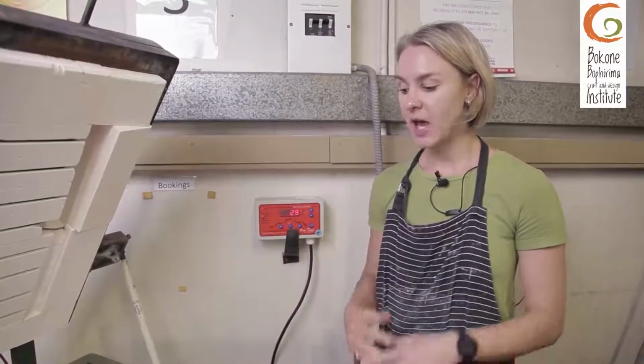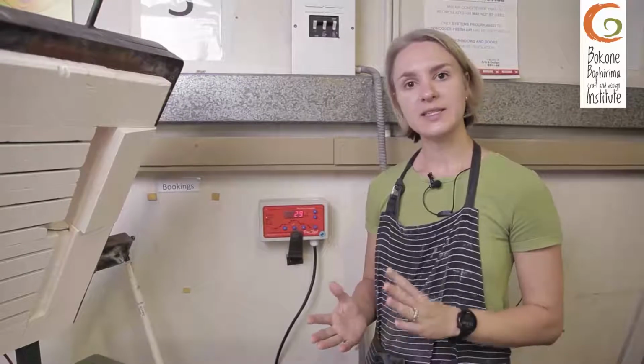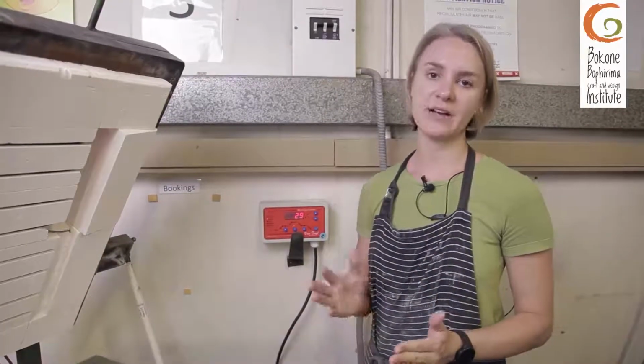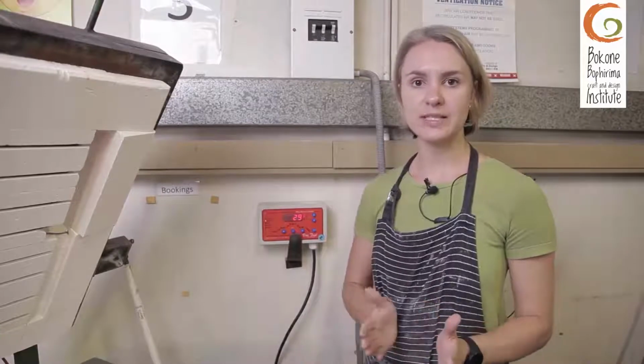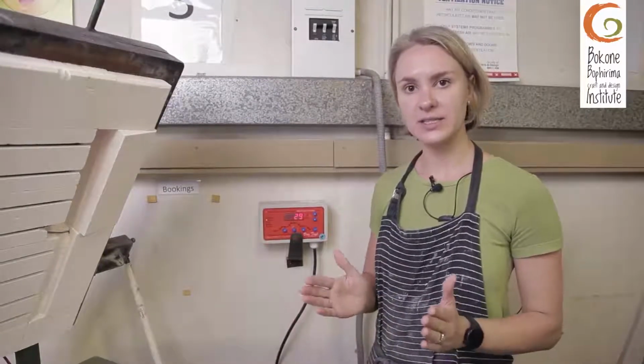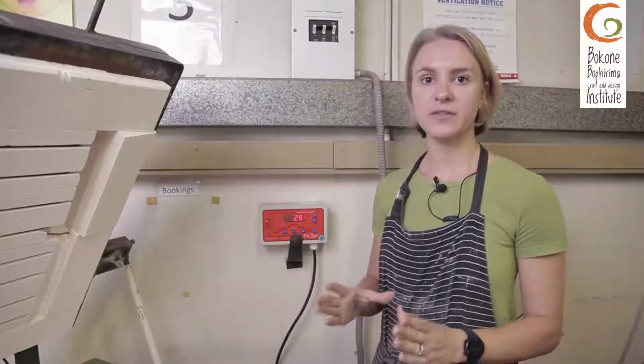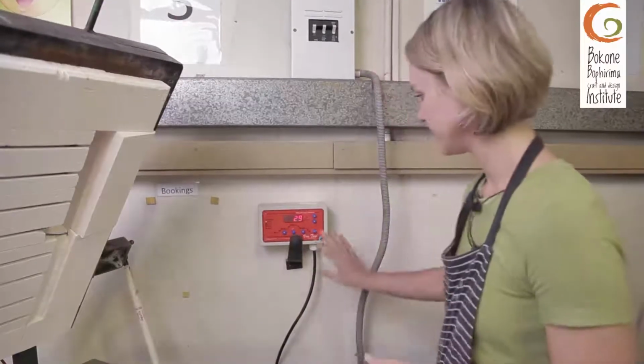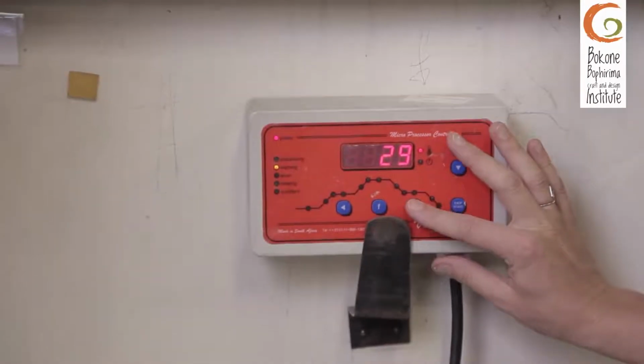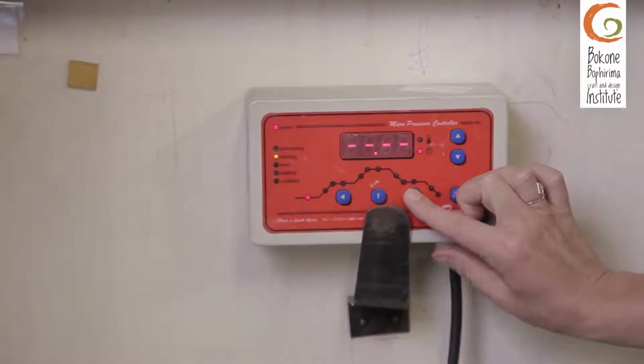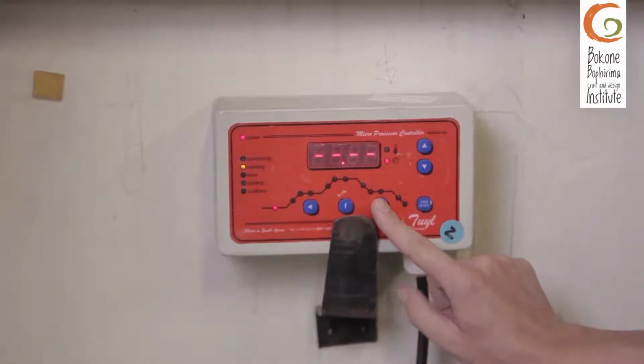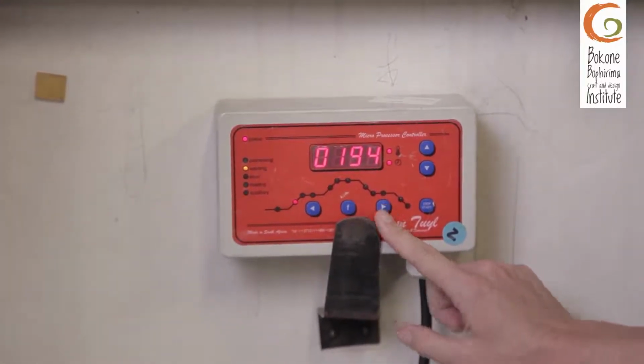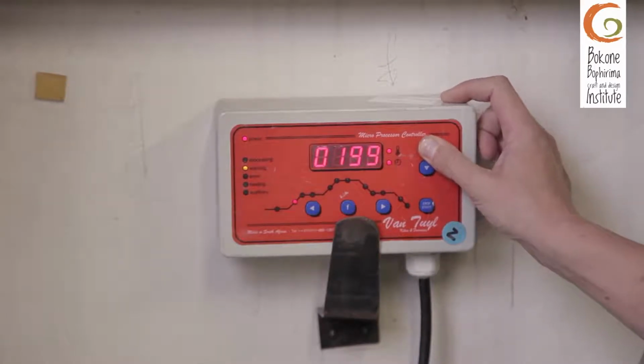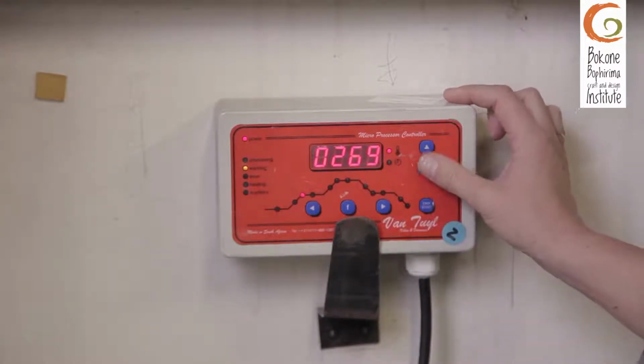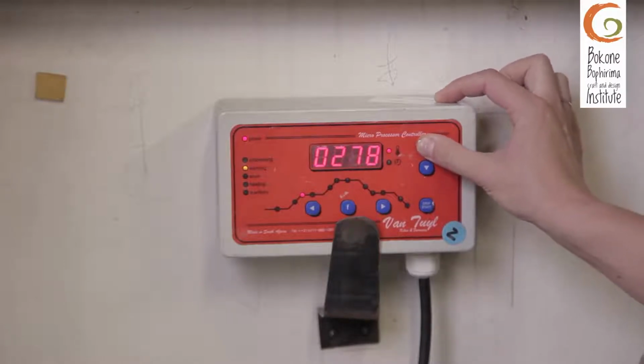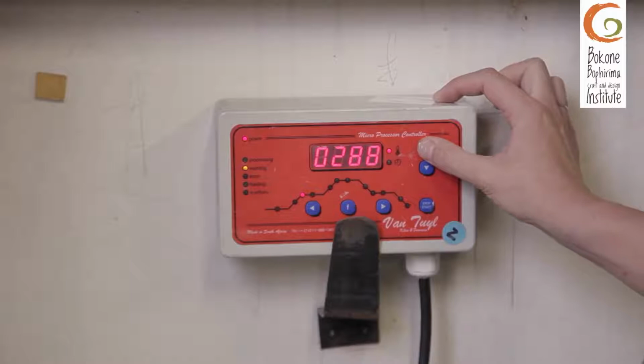I'm now going to discuss the low temp enamel firing. This temperature ranges between about 540 to 580. So just keep in mind to always do test pieces beforehand to make sure you found your desired firing top temperature point before starting your final piece. My top temperature with this will go up to 580. First, our delay. We do not need a delay, so we're going to pass that section. And we're going to take our glass up 200 degrees an hour, up to 300. And why 300 is because I'm actually going to pass the section. I'll explain that now.